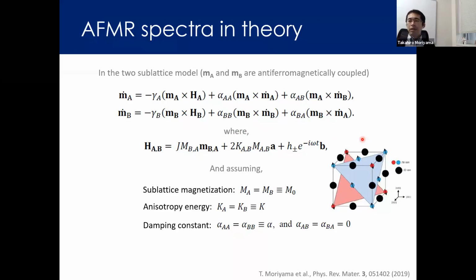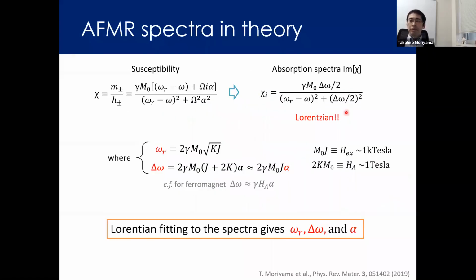For nickel oxide, it's a simple magnetic structure. So assuming the magnetic properties of sublattices A and B are identical, we can simplify all these parameters, like sublattice magnetization, anisotropy energy, and damping constant, something like this. And we can solve these simultaneous equations and obtain the frequency-dependent susceptibility. Okay.